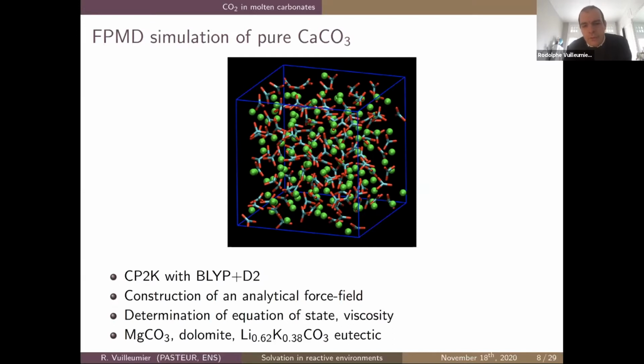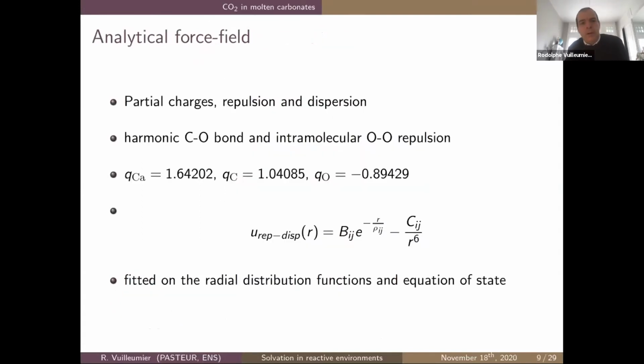So the path that we took was to construct an analytical force field, a simple one with partial charges, a simple exponential repulsion and dispersion attraction, which was fitted on the first principle MD results. Of course, this is a typical step that you do in this situation. At the moment there is a lot of work to try to replace what we did there with artificial intelligence and machine learning techniques. This is still at the verge of what these techniques can do, because we have many species in the system, not only carbon and oxygen, but also, if we go to alkali, lithium, potassium, magnesium, calcium, and there are too many species for the current state of the art machine learning.